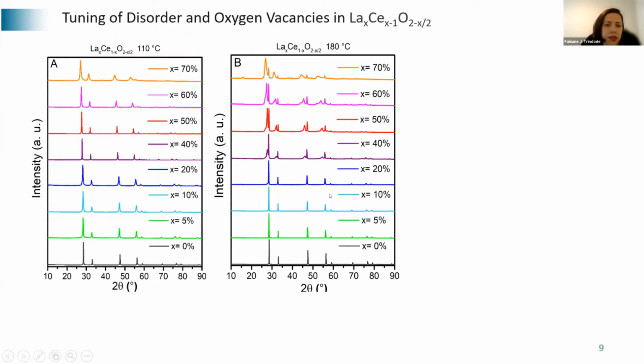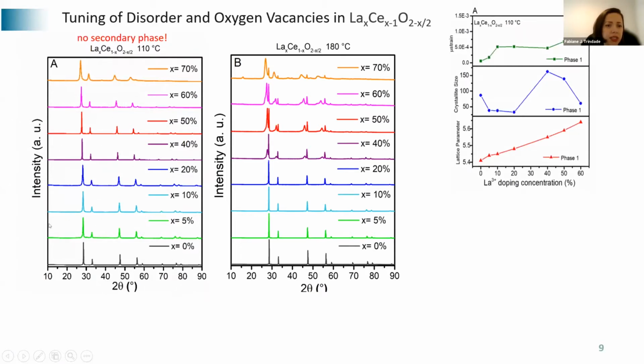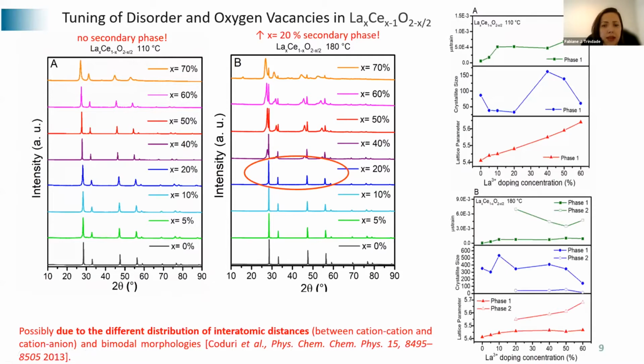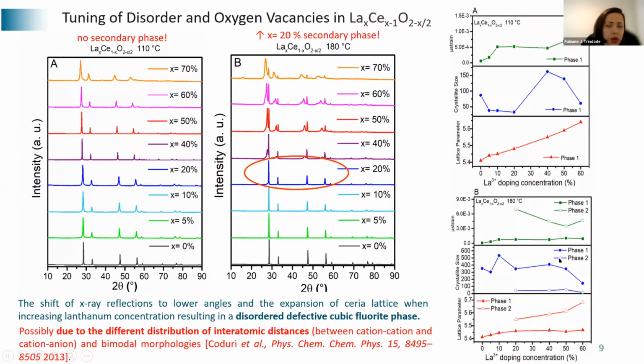After doping the Ceria nanoparticles, the Ceria fluorite structure was essentially maintained for the 110 degree series, and no secondary phase was found. On the other hand, for the series synthesized at 180 degrees, up to 20%, a secondary phase was found. This is probably related to the bimodal morphologies, and also to different distances between cation and anion. As we can see in the figures showing the lattice parameter, there is a shift to lower angles, which proves that this fluorite is a defective fluorite structure.